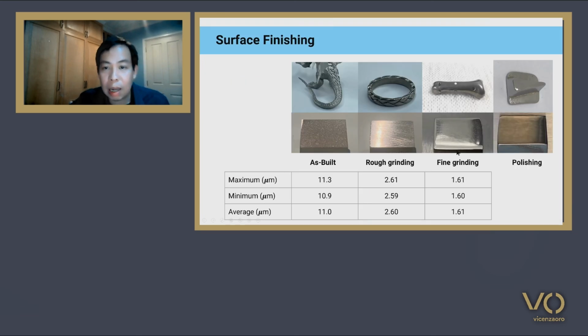Surface finishing, we treat these samples just like jewelry materials. You see the tail of the dragon here. This is the as-built roughness, and we have rough grinding and fine grinding, and also polishing techniques. These are all quite straightforward. Actually, we didn't try anything new except the fact that these are all dry process. Titanium doesn't like water.